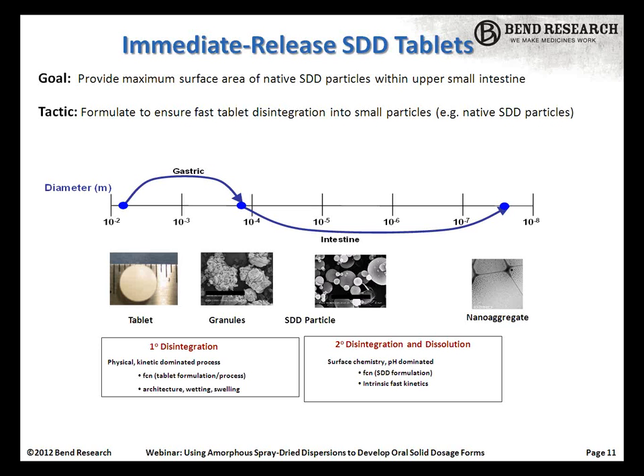We have found that although capsules do work well if they're formulated, by the time that we've gone through the work of formulating the capsule, we might as well almost just formulate the tablet, because the tablet is normally the ultimate goal for most of our dosage form work, to deliver a tablet for the further downstream. So our goal in developing a tablet is to, as rapidly as possible, get the tablet to disintegrate, macro disintegration, such that it reforms the granules and then back to the native SDD particles as rapidly as possible, such that these formulations can then be within the absorption window, and we can take advantage of the high energy nature and get full drug absorption.